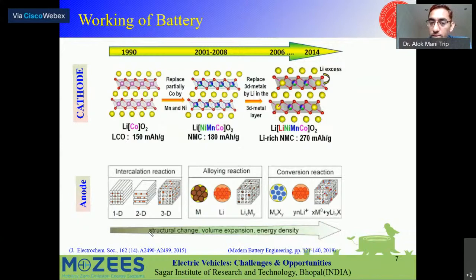Similarly, if we see the anode side, because both are very important, because one is releasing the lithium and the other is accepting the lithium. So anode, conventionally, when the reversible battery came, it used graphite. Why graphite? Because graphite has layers of graphene, and those layers can include the lithium ion inside. When it includes the lithium ion, there is very minimal volume expansion, less than 10%, and then it releases it when needed. And the second benefit was that it is almost near to the lithium intercalation potential.